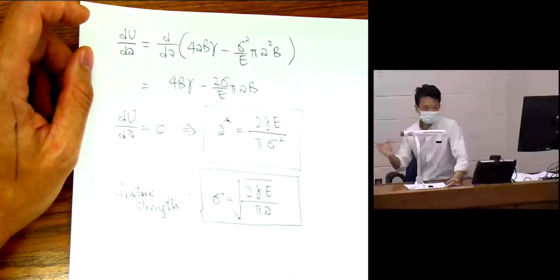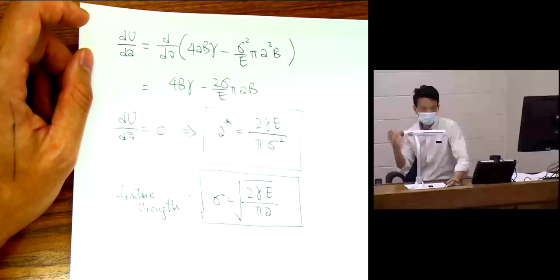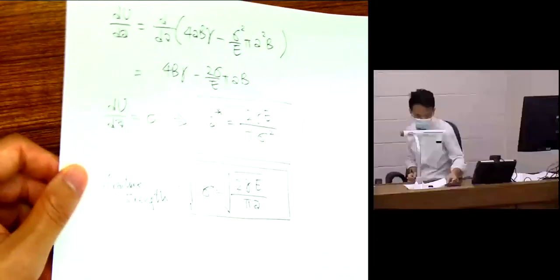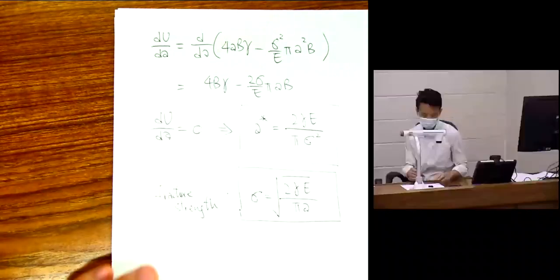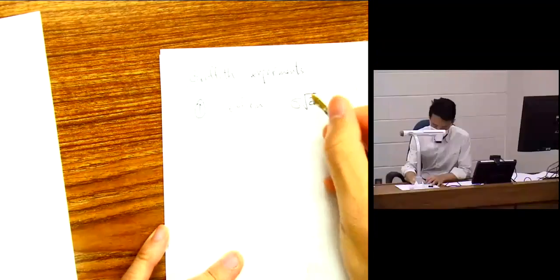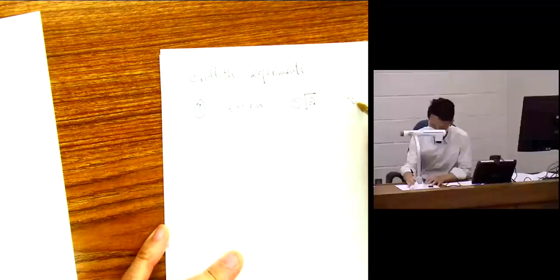This is a material property. They give me concrete, I can't make elastic modulus different. So, in other words, what he needs to show first of all, by rearranging this equation slightly, is that the first objective is to confirm sigma times the square root of A is constant.